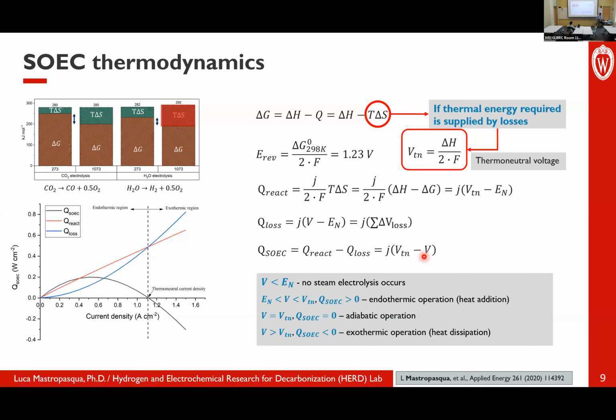Without going into all the maths here, the chart on the left shows that these devices can operate at different thermal balance conditions. If you operate at low current, on the left-hand side of this chart, the black line shows a positive heat to the system. That means that the system is consuming heat. It's an endothermic process. The water splitting reaction is an endothermic process. So at low current, the system can consume heat.